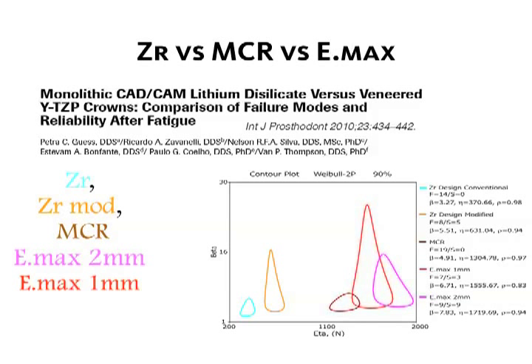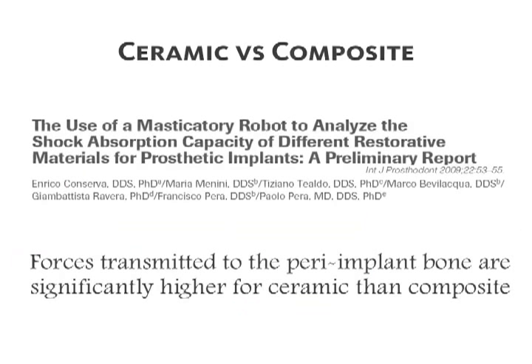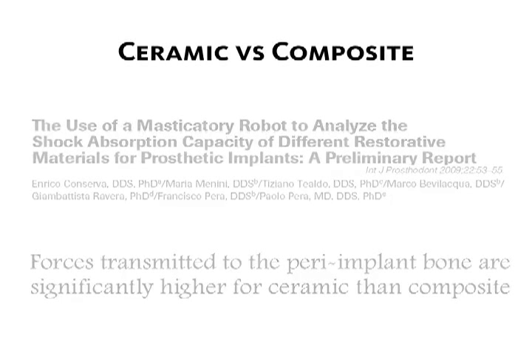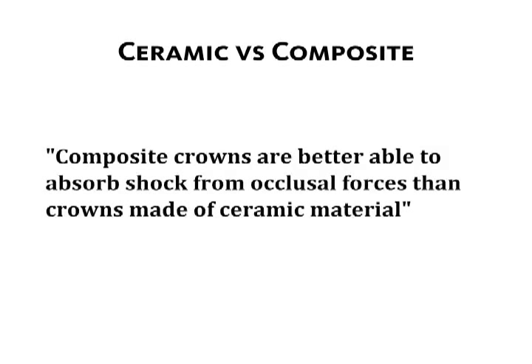Although the reliability of materials for prosthetic reconstructions under fatigue loading has been described in several papers, their specific behavior when used for implant-supported restorations and their effect on bone response have been explored to a very limited extent and somewhat anecdotally. For implant-supported single crowns, for example, it has been shown that forces transmitted to the peri-implant bone are significantly higher for ceramic than for composite. These authors concluded that composite crowns are better able to absorb shock from occlusal forces than those made of ceramics.